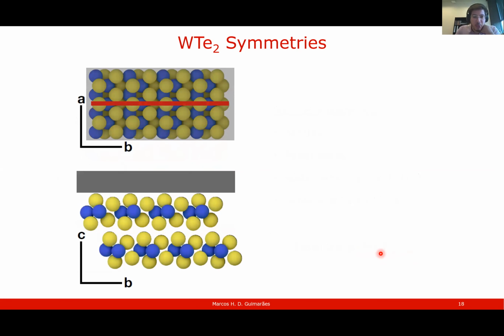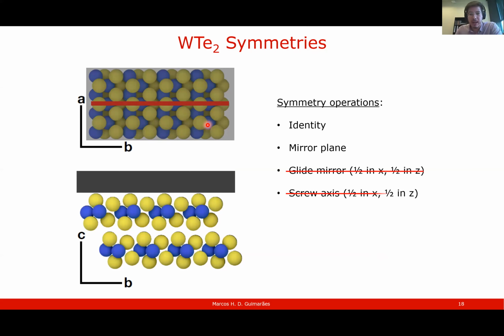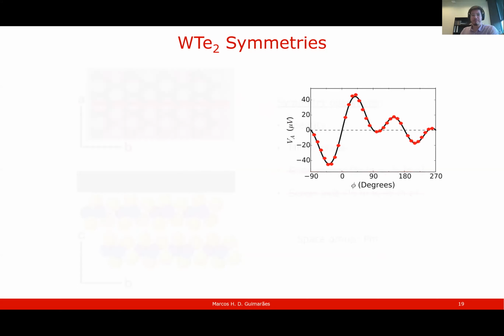However, now if you couple with a ferromagnet, so we put the ferromagnet there on top of this tungsten ditelluride, we reduce the symmetries. So we lose all the translations that we had, which will make a translation in the Z direction, just because now we have this interface over there. And this reduces the symmetry operations just to the identity and the mirror plane, which is at the BC plane. And this has space group PM.